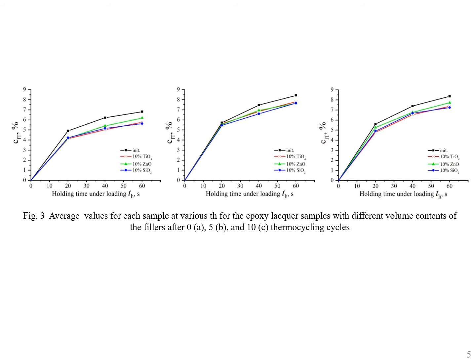A load of 1 N, a loading time of 40 seconds, and a holding time under load of 0, 20, 40, and 60 seconds were selected as loading parameters to study creep. The behavior of creep as dependent on the holding time is qualitatively the same for all the samples tested. For the filled lacquer samples, the values of creep decrease on the average by 15%. The obtained data testify to the absence of a significant effect of modifiers on the viscosity properties of the polymer, obviously due to the lower content of oxides in the coating.